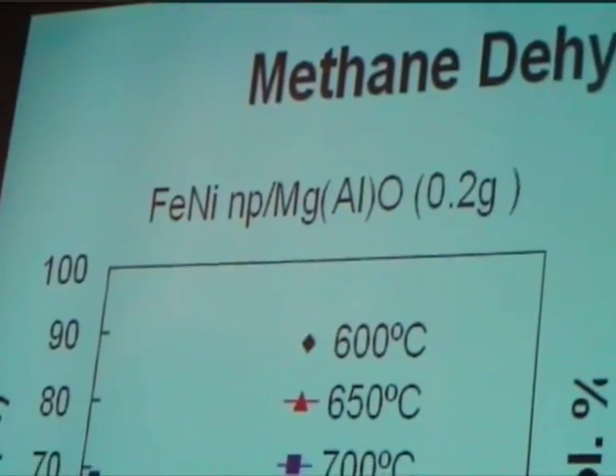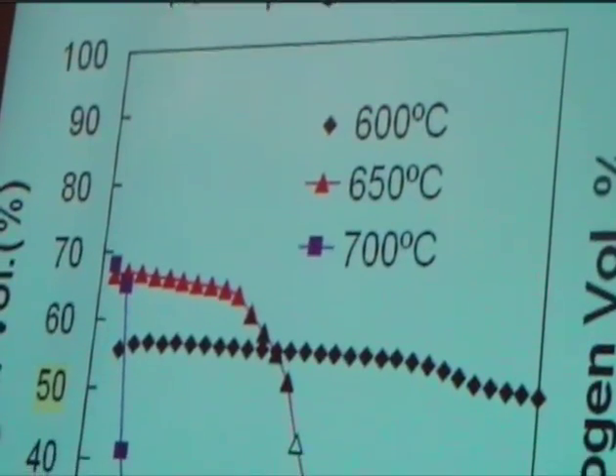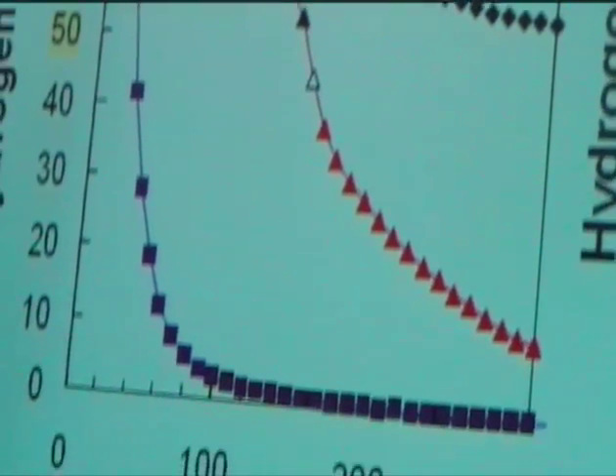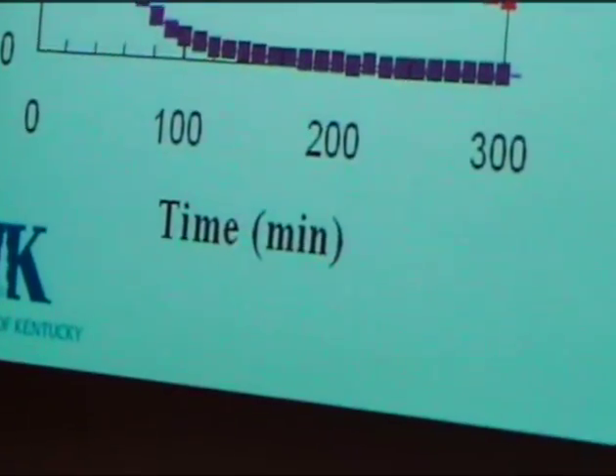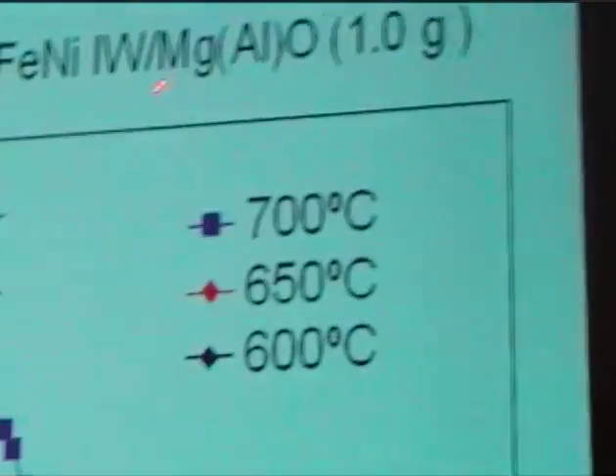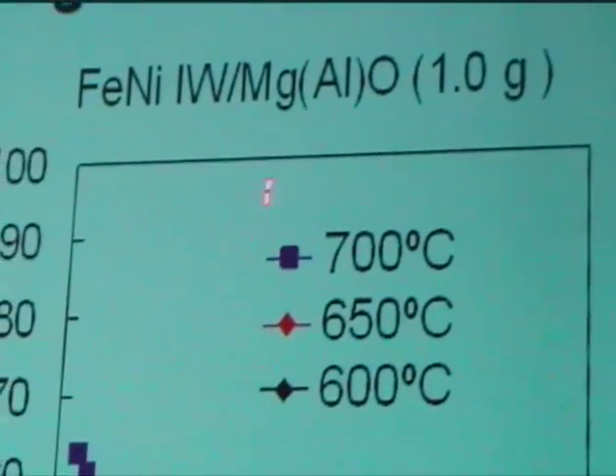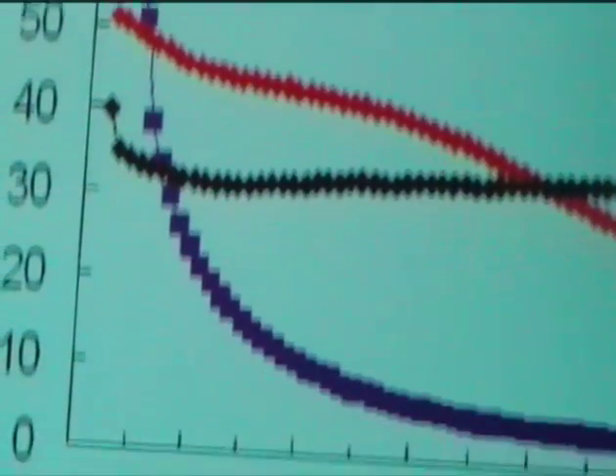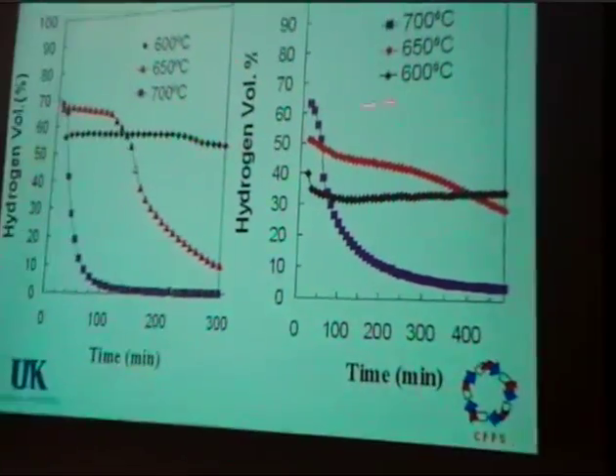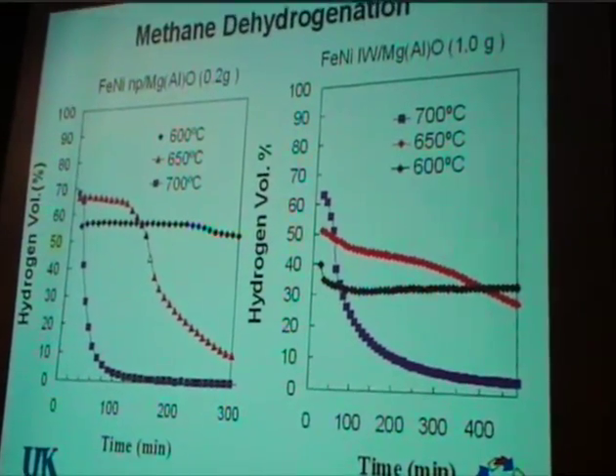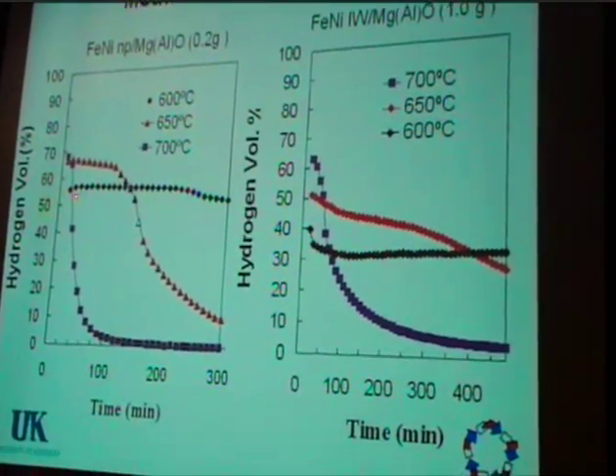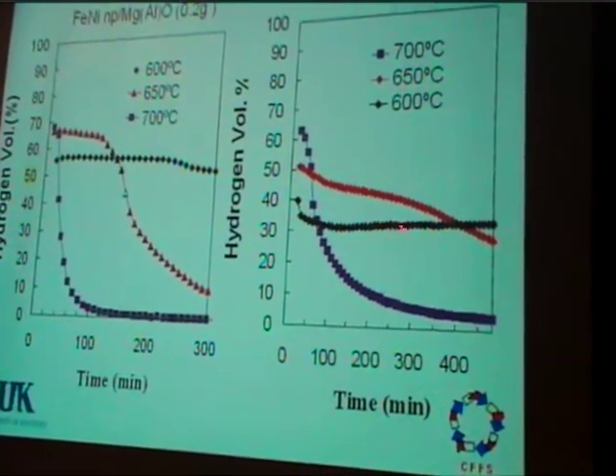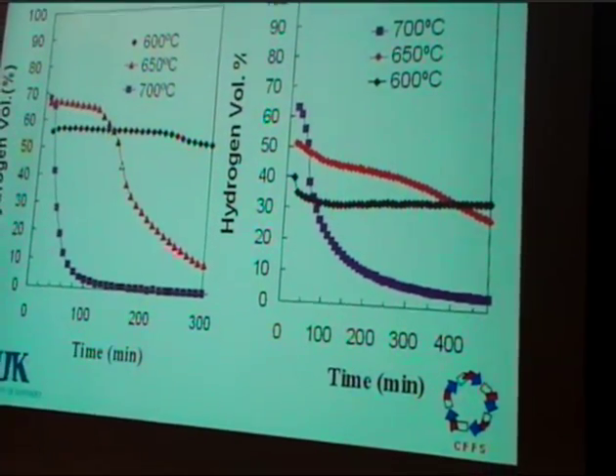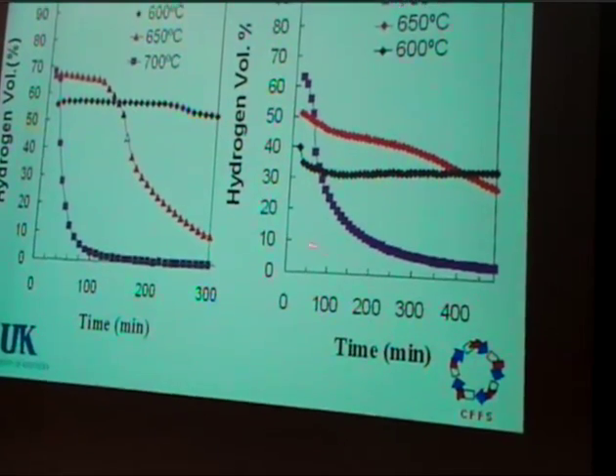And here are some results for methane dehydrogenation. The iron nickel nanoparticles on magnesia alumina on the left, and iron nickel prepared by incipient wetness on magnesia alumina on the right. And at the 3 temperatures indicated here, you can see the nanoparticles are considerably more active for all of the temperatures where they are active.